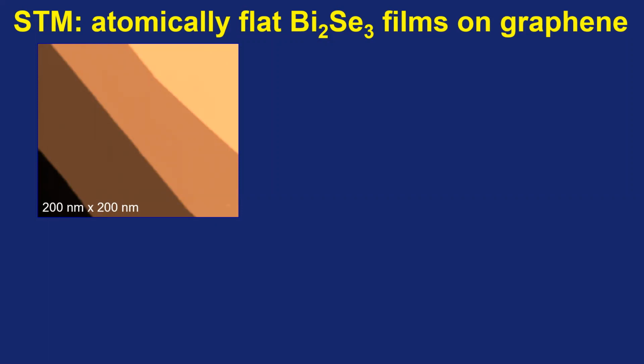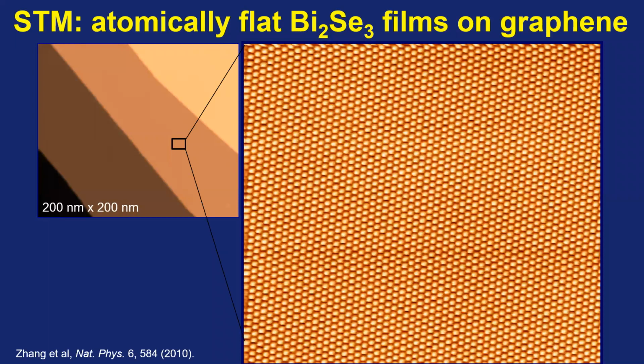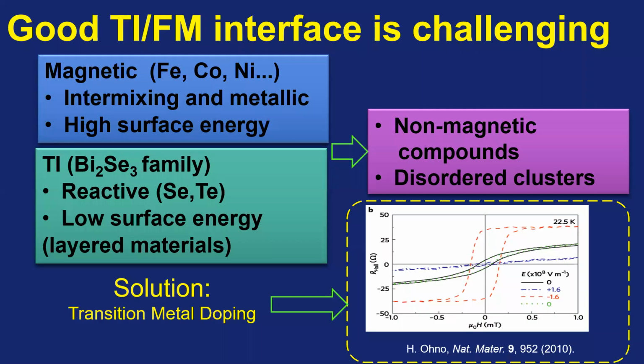So this is the large scale STM image. We can see the terrace is atomically flat, and this is the atomic resolution STM image. We can clearly distinguish the selenium atoms on top of the bismuth selenide. And in this typical site, there are no defects. So that also confirms the quality of the MBE grown film is very high. And we use MBE to get the thin film of topological insulator.